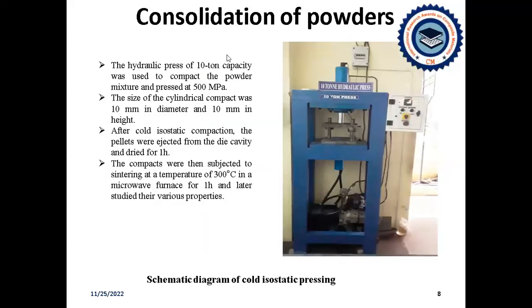This consolidation of powder was performed using this hydraulic press at a pressure of 500 megapascal. The powder was compacted, and the cylindrical compact dimension was 10 mm in diameter and 10 mm in height. After this cold compaction, it is dried at room temperature. Then the green pellet was taken out from the die, and the compact sample is subjected to microwave sintering at a temperature of 300 degrees Celsius in a microwave furnace for 1 hour duration.